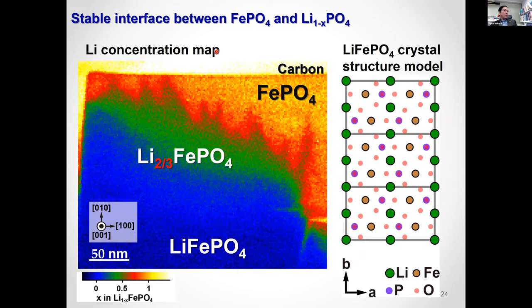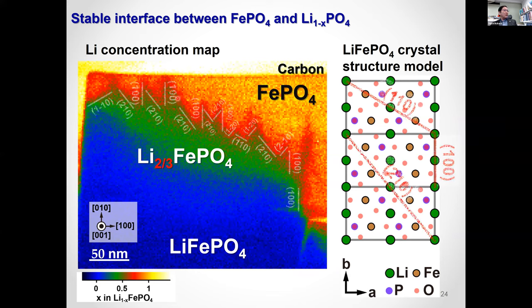This is the lithium concentration map again. So this is an intermediate phase, and the diffusion occurred from inside to the surface. And it is interesting that at the diffusion front, you can see a facet structure is formed like that. The facet is parallel to a low index plane. Therefore, the diffusion occurs this way. At the front, a facet is formed, and this facet is diffused to the surface, and this intermediate phase is dragged. This is actually the phenomenon of lithium diffusion.